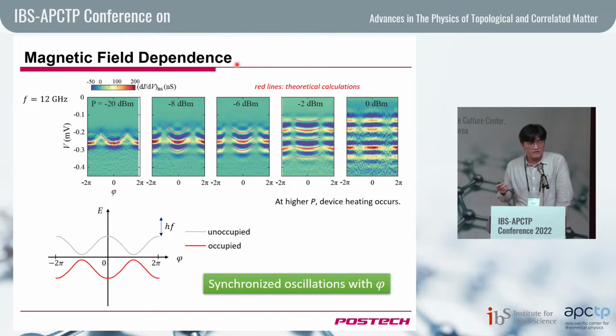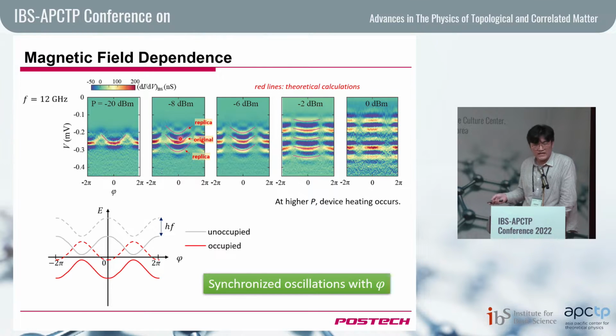Just for a sanity check that the replication is really coming from the underbound state, we also apply a magnetic field, and the original underbound state oscillates as a function of external magnetic field, as I showed in the previous slide. And the replicated state also oscillates in the same way. So that probably comes from the original state that is oscillating as a function of magnetic field. That's another way we can check that the additional dI/dV peak is actually related to the original state.